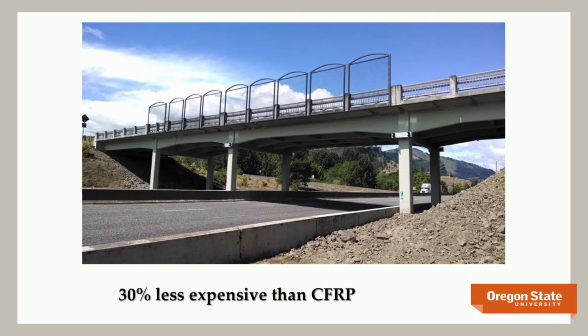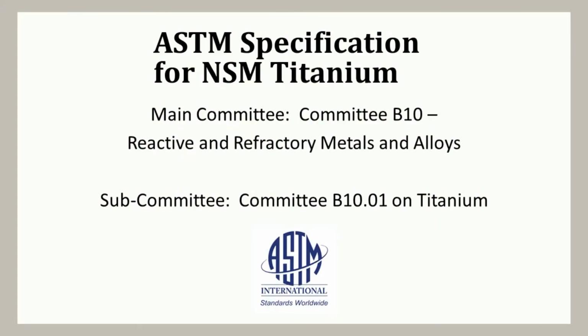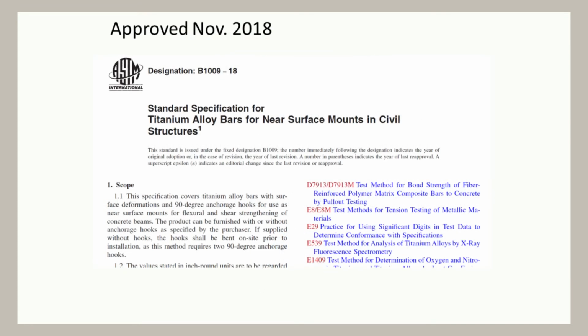Because it was the first application, they actually had a carbon fiber retrofit, and the bids came in, and even though nobody had ever used titanium before, it was 30% cheaper than the carbon fiber. How do you use this? Well, there's a brand new ASTM specification, which comes out of Committee B10, the reactive and refractory metals and alloys, aka titanium. It was approved last November. So you now have a brand new standard specification for titanium alloy bars for civil infrastructure.